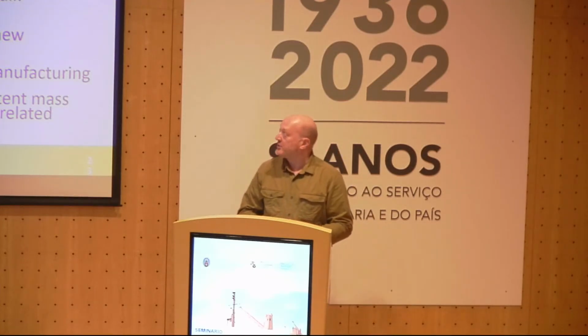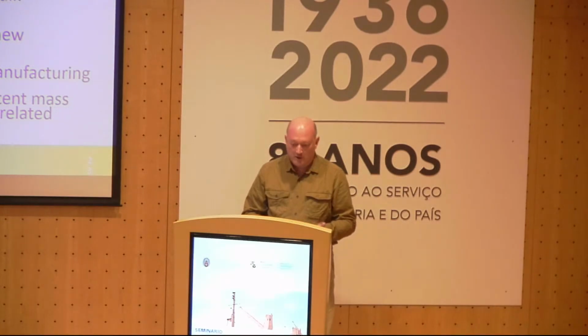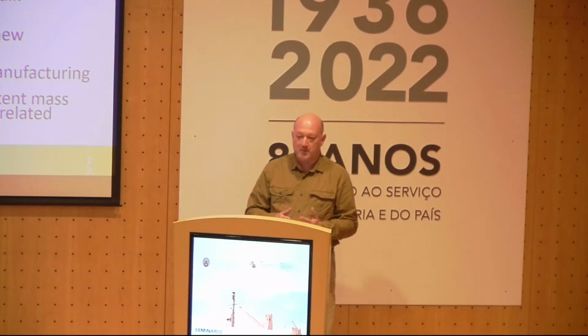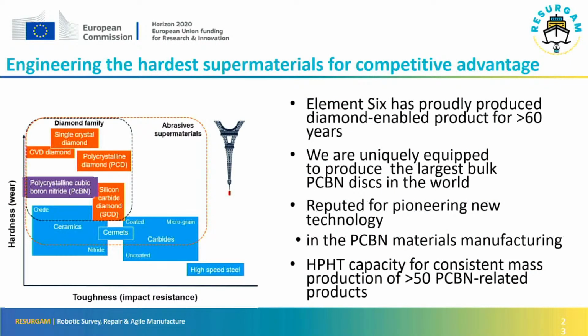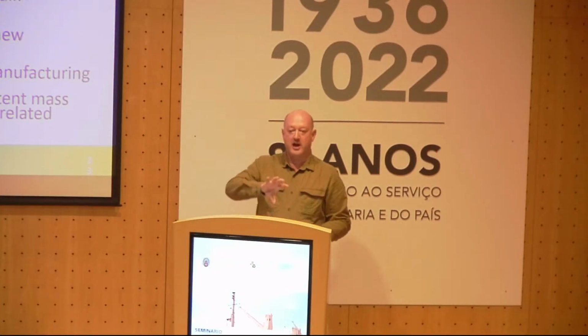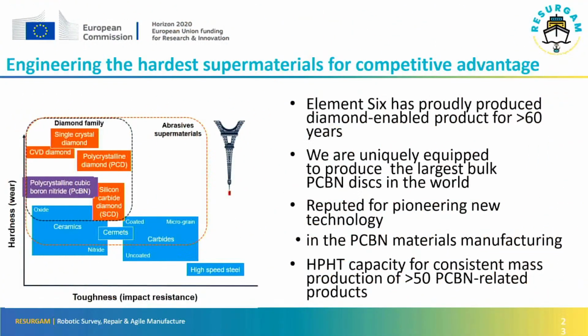So one of the materials in their portfolio are super abrasives based on polycrystalline boron nitride. And basically they take boron and nitrogen, they put them in a press, subject it to an immense pressure and heat it up at the same time. And basically they explain that if you imagine putting those materials into a small canister the size of a tin of baked beans and then turning the Eiffel Tower upside down and balancing it on top of that tin, that's the kind of pressure that they used to manufacture their polycrystalline boron nitride.